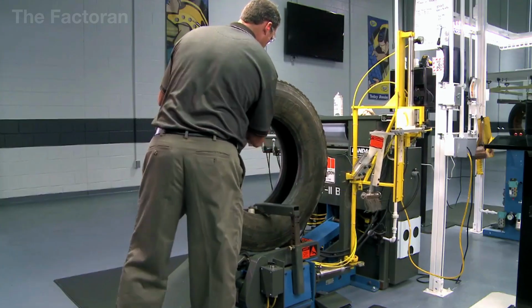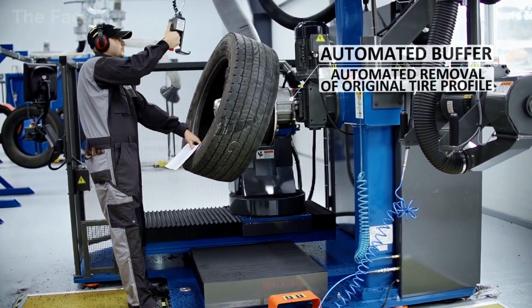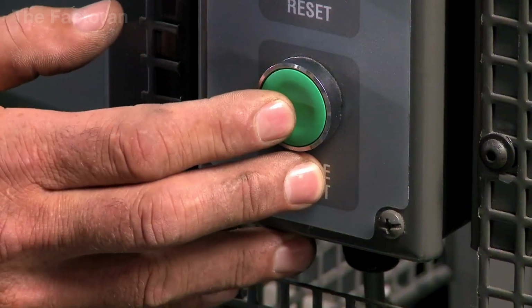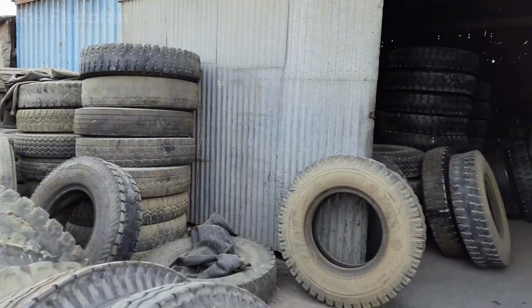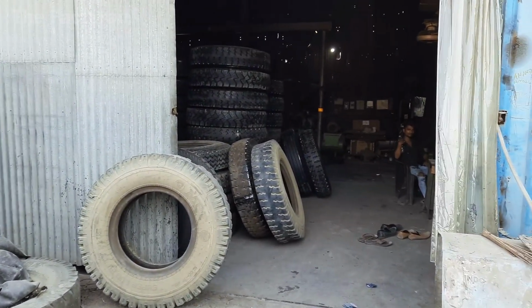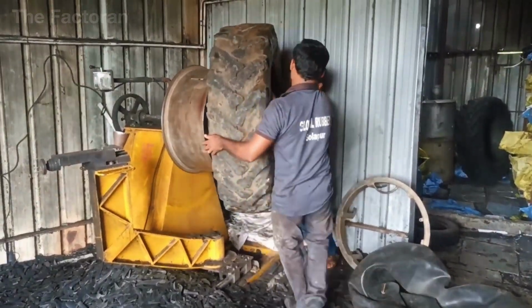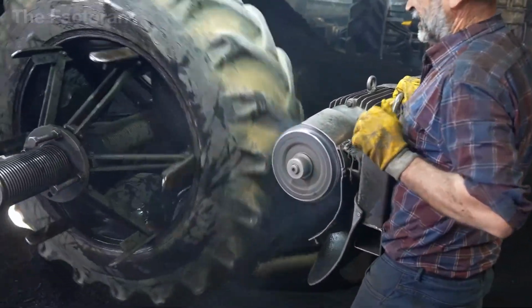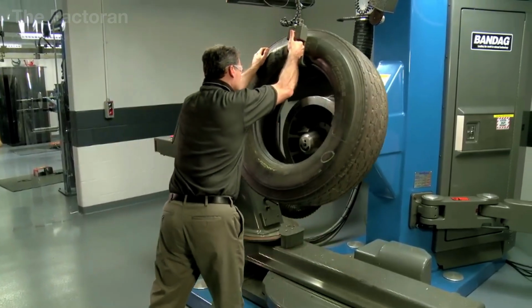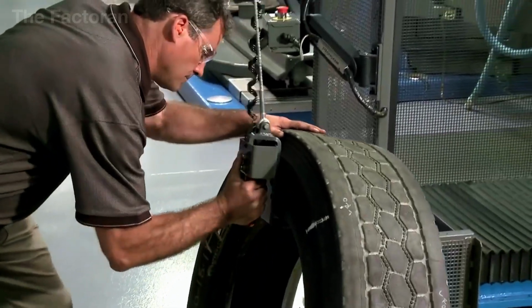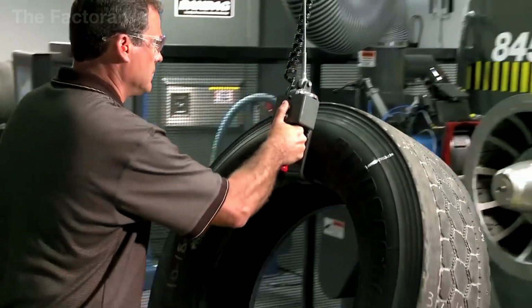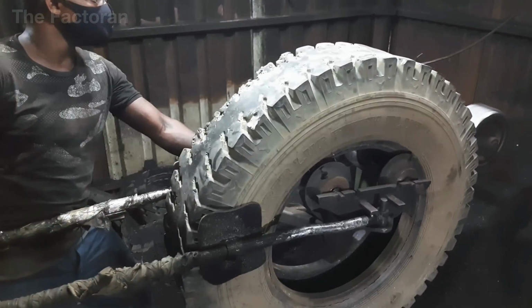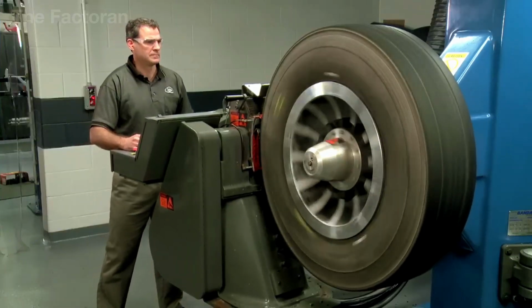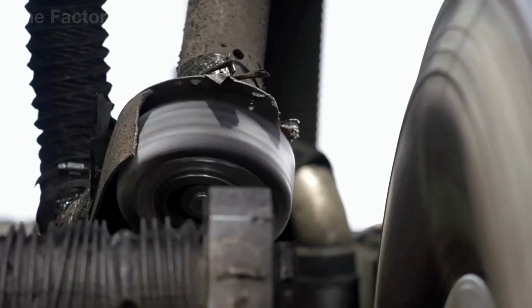Once the casing has been selected, it is sent to the buffing machine, a specialized piece of equipment with grinding heads that spin at high speed. Here, the entire old tread is shaved away, exposing the undertread beneath. The surface of the tire is roughened and reshaped to the exact diameter and roundness required, ensuring it stays balanced when rotating. The grinding depth is only a few millimeters, just enough to remove the worn rubber without damaging the casing structure. Modern machines are also equipped with suction systems that capture rubber dust as it is produced, reducing pollution and lowering the risk of fire.